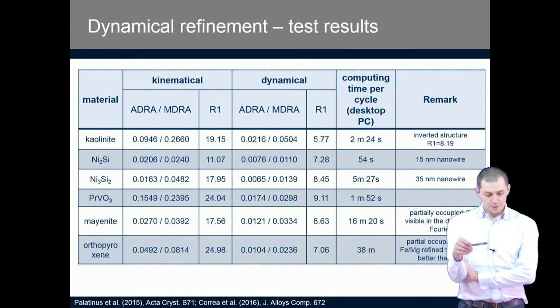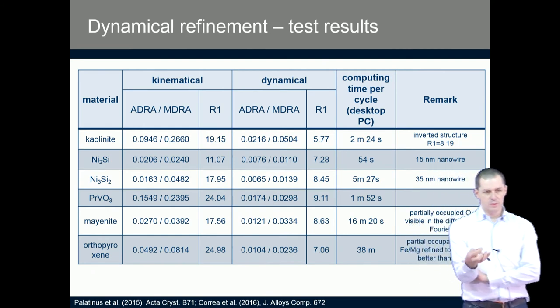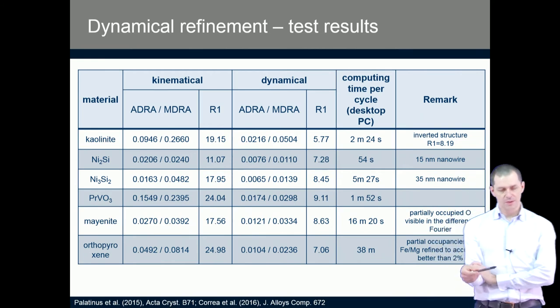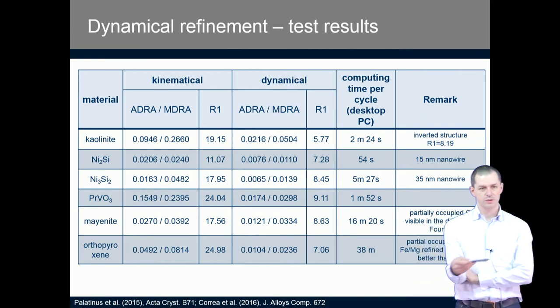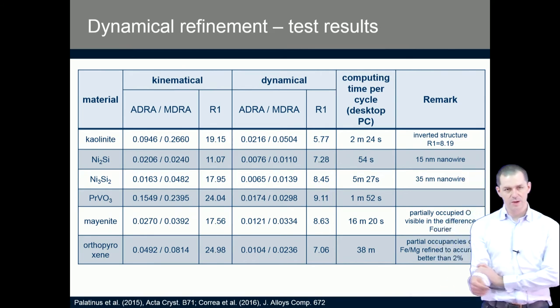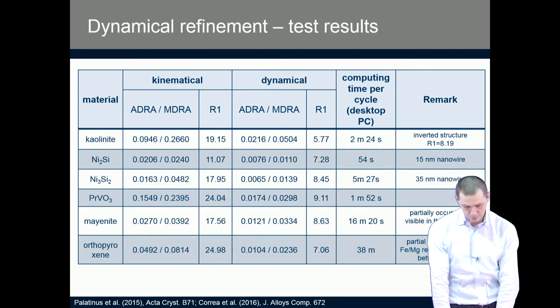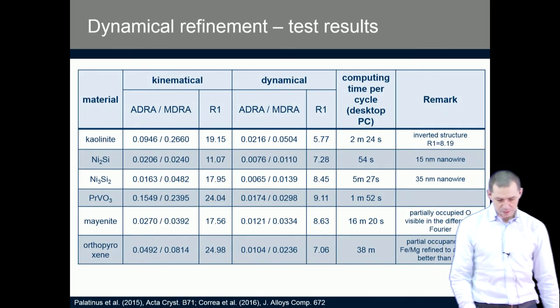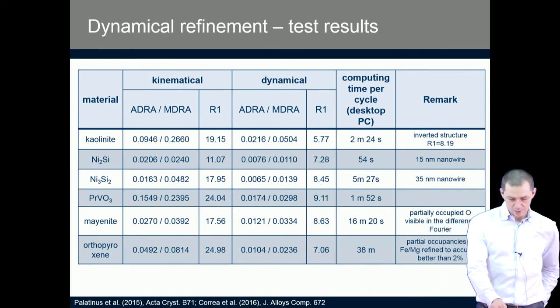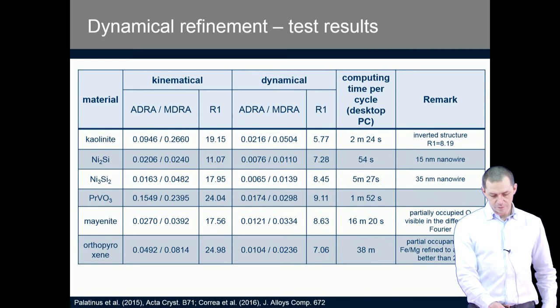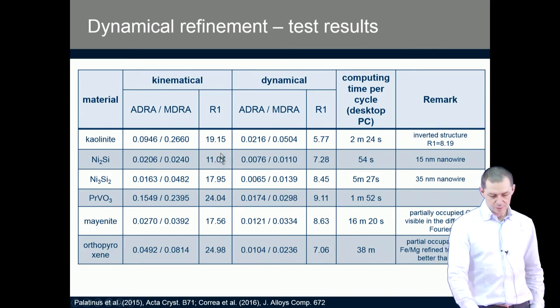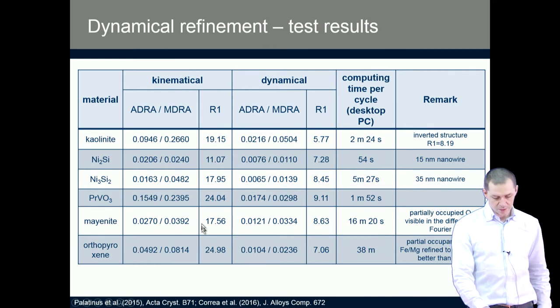At the beginning of the work on this project of dynamical refinement, we did quite a lot of tests on known structures for which we had reference X-ray structures, so we could compare how accurate results we can get. And this is a table showing some of them. I will not go through all the numbers, but just to highlight some of them. The first column is the result of kinematical refinement, the second column is the dynamical refinement, and you see the comparison of R values, which are typically around 20%. This is an extremely good case of 11%, otherwise it's close to 20 or more.